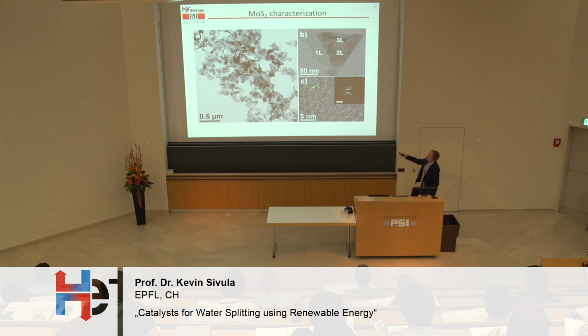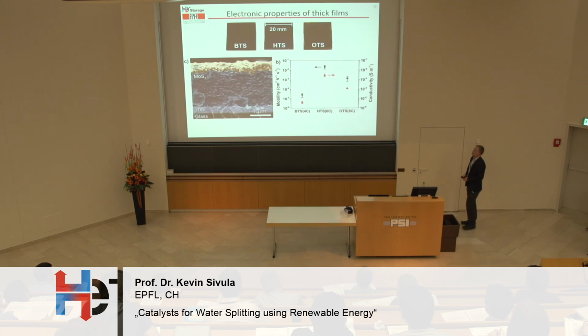In addition, the centers of these flakes have good crystallinity, which we hope could help facilitate charge transport to those edge sites. Still, film formation was a little bit difficult with these samples. We were able to make thick films using a special drop casting technique and letting the solvent evaporate very carefully. And you can see here they all look very black using the different surfactants.